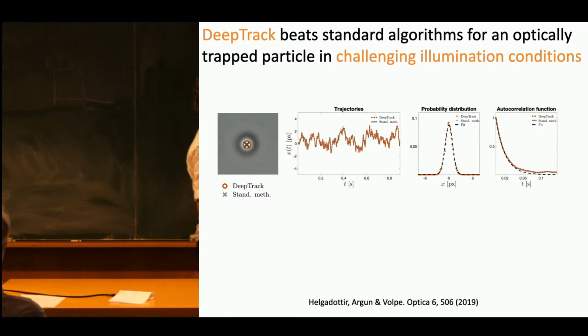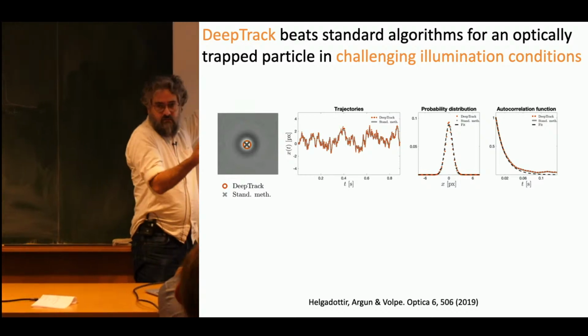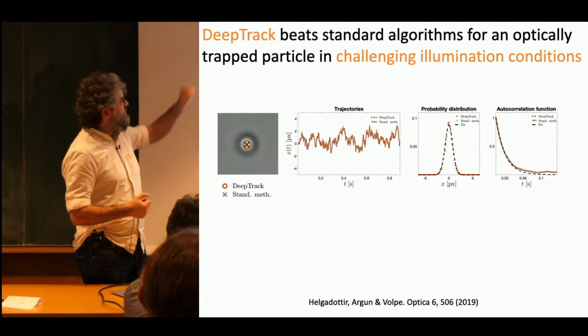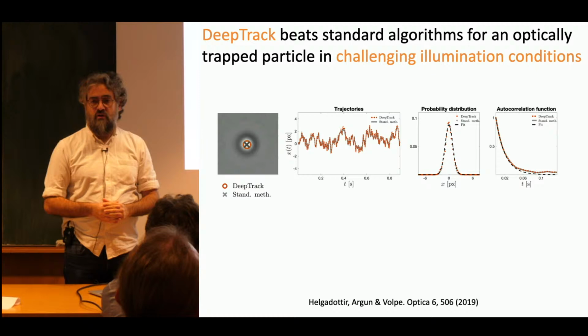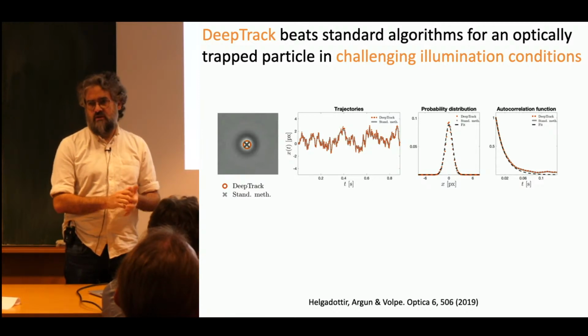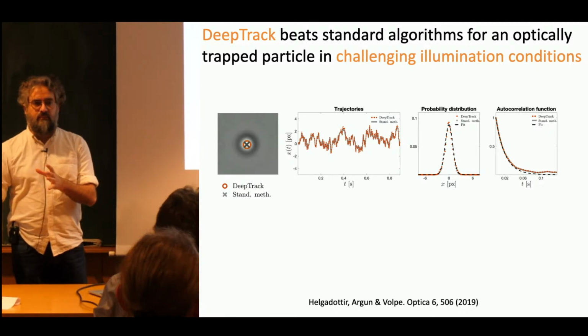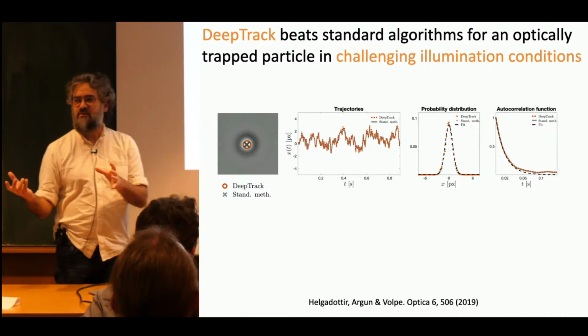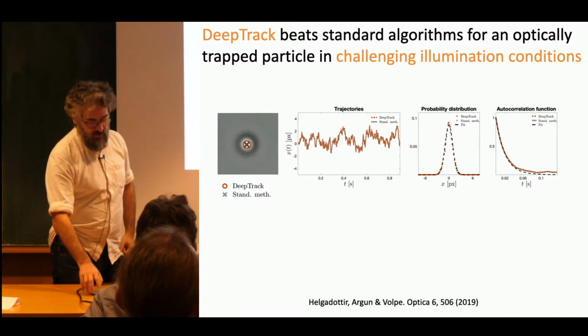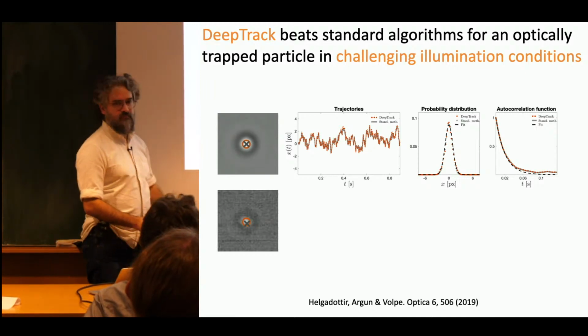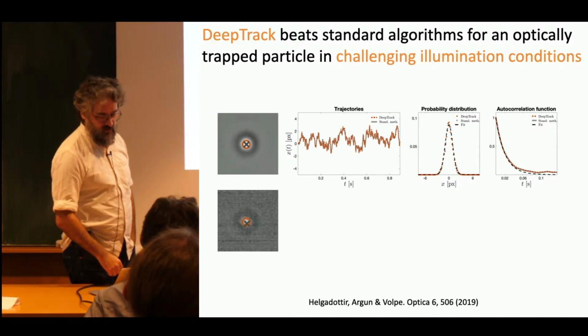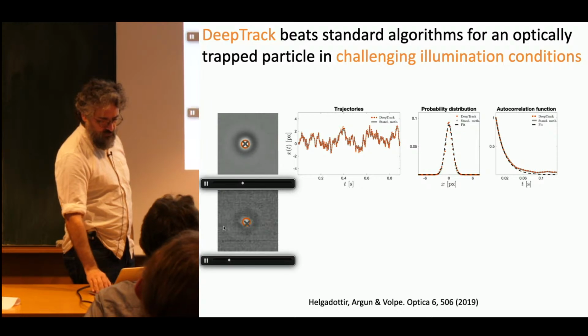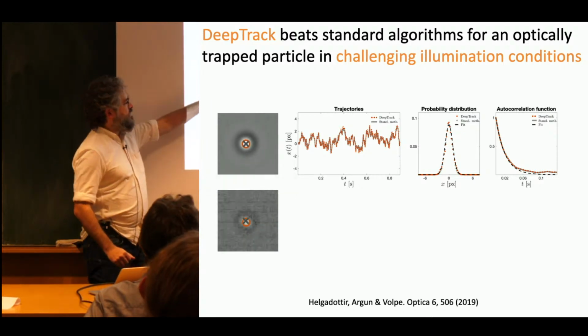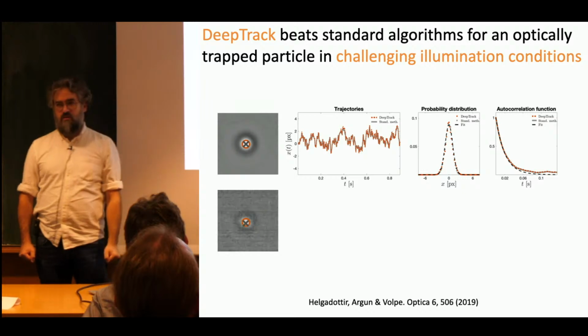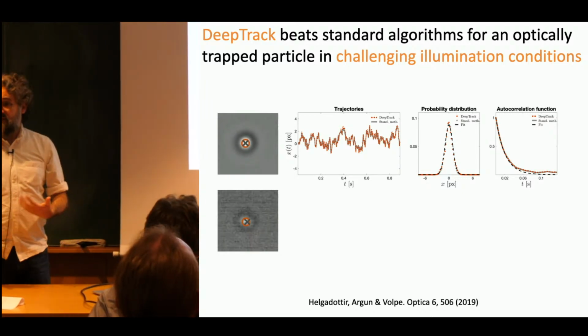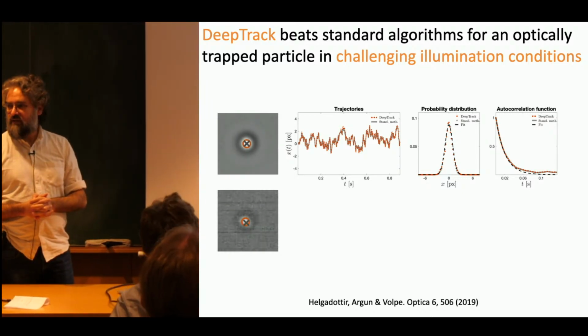But then what we did experimentally, in our lab, with this particle in an optical trap, was to switch off the high quality LED illumination and switch on an incandescence lamp next to the setup. As you can understand, that's a very bad way of illuminating your microscopic sample. And what you get is this video. You see that now you have all possible kinds of noise. And you see that now DeepTrack seems to track the particle very well. But the standard algorithm doesn't really manage to find the particle.